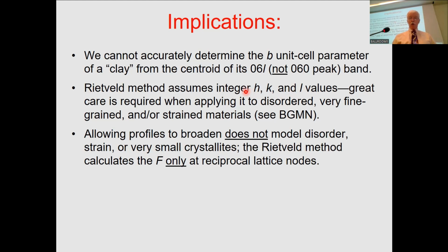Finally, don't think that, oh, I can broaden my diffraction peaks if I put in a series of split Pearson 7 peaks, I can fit my diffraction pattern. You can fit it. What does it mean? It doesn't mean much. So don't fool yourself that just because you can fit your diffraction pattern with the Rietveld method, that the information that you get is accurate or real.